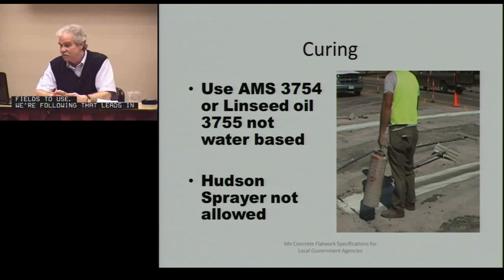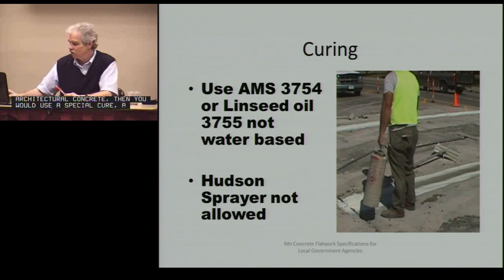Again, this cure, the Hudson sprayers won't be allowed. They won't use them very often. They'll get plugged up. There's so many solids here. But you can use the AMS 3754 or linseed oil of 3755, not water-based. If you get into the colored architectural concrete, then you'd use a special cure, the fugitive dye that the DOT has. So you don't ruin your color is the idea. So curing's a little different here.